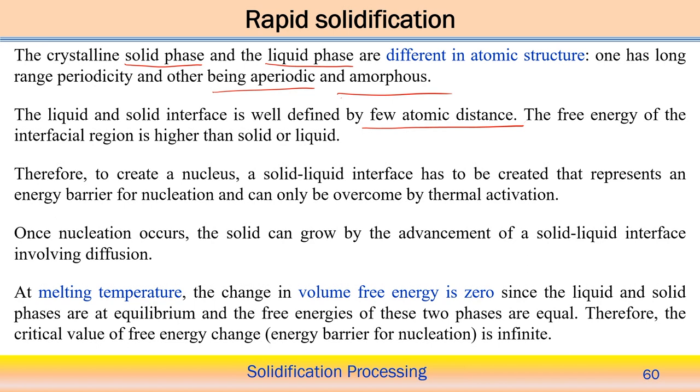In this case the free energy of the interfacial region is usually higher with respect to the solid and the liquid phases. So at the solid-liquid interface the energy of the interfacial region is much higher compared to the solid and the liquid phase, because creating a nucleus at the interface represents an energy barrier to starting the nucleation process. It is necessary to activate this process through thermal activation to overcome that energy barrier.